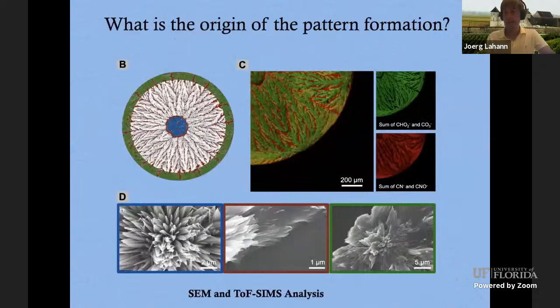So where are those droplets coming from? Basically, obviously, we have a buffer system and a protein. We have done a little bit of analysis. You can do SEM first order. You see the morphology. You see a little bit of differences in the core region, which probably looks a little bit more like salt crystals than what you see in the in-between region. You see some kind of a hybrid, and then probably outside you see maybe a little bit more of the protein, it looks like. And so we can confirm that then with TOF-SIMS as well.